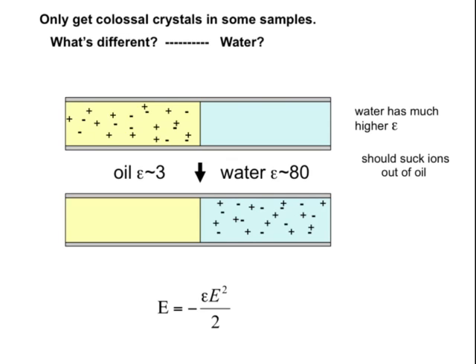If you put water next to it with a dielectric constant of 80, the ions would rather be, according to electrostatics, they have an energy of minus epsilon e squared over 2. They would rather be in something with a high dielectric constant. So the ions here should suck over to the water. The water should just clean out the ions from the oil system. And that would explain why suddenly the screening length was very large and why we were getting this effect.